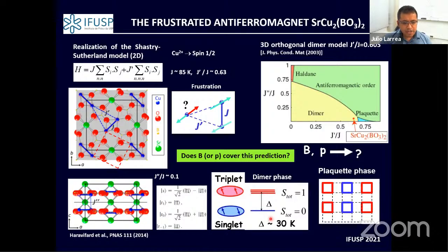Another interesting point: if you look at the possible different orders that can arise from changing the ratio, theoreticians predicted you can obtain different phases. Here I show a more general phase diagram for this dimer model, strontium copper borate, according to the ratio of J prime over J.